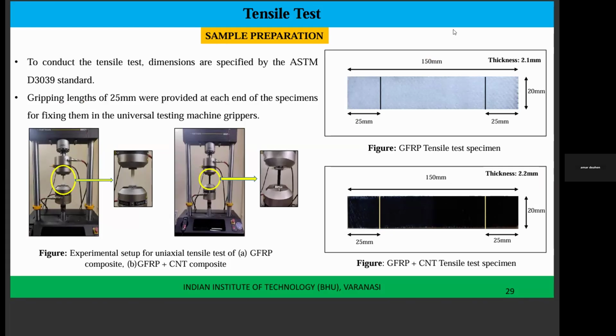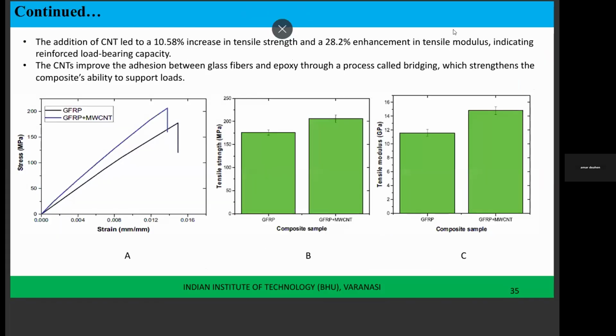We have compared the pure glass fiber based polymer composite with the glass fiber with multi-wall carbon nanotube mixed polymer composite, and we can see there is an increase in the tensile strength and also an increase in the stiffness, the tensile modulus. Next slide, please.